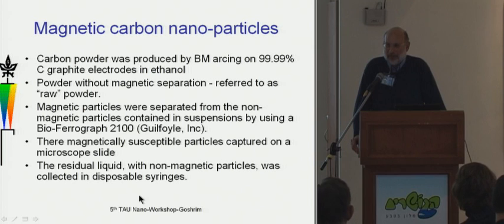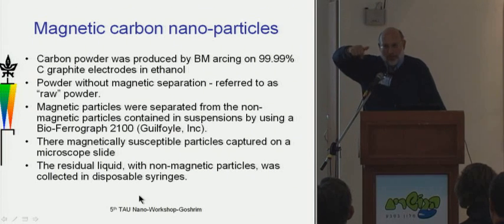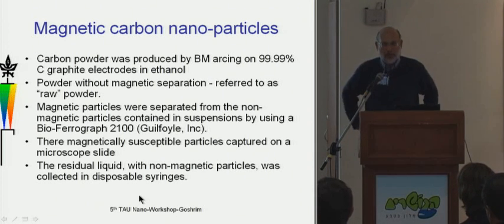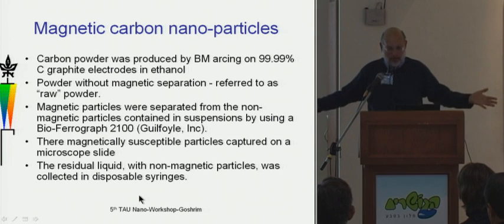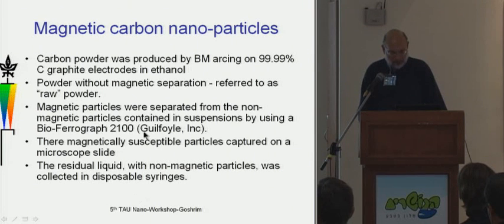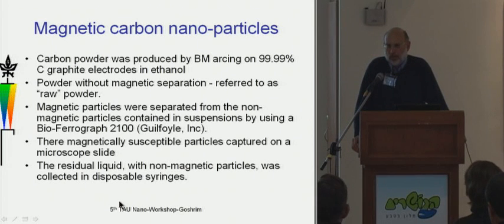And actually what happened is we had this material and put it on a magnetic stirrer, and before we put the magnet into the beaker, we noticed that the fluid started to rotate. Couldn't understand what the hell was going on here. So we had the suspicion that maybe some of the particles produced were magnetic, but how could that be? It's just carbon. Well, at any rate, with a little bit of help from Noam Elias, we took this liquid and passed it through what he calls a bioferrograph, which is basically small capillary tubes where you place a strong magnet. And any magnetic particles within the suspension are collected on the wall of these glass capillary tubes.